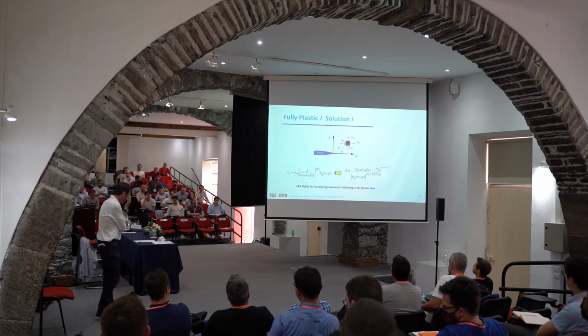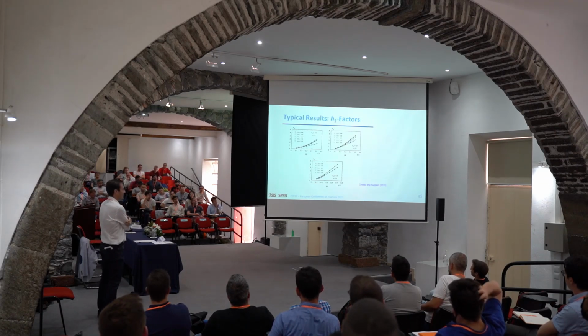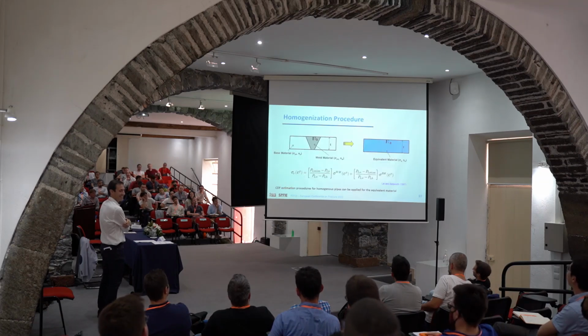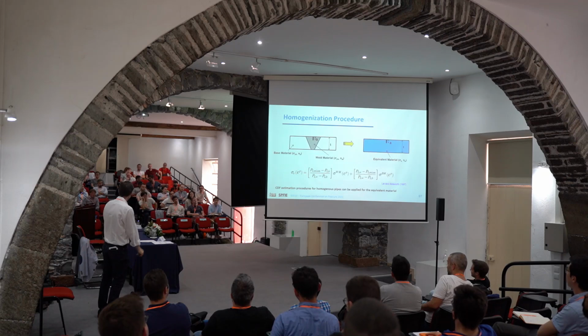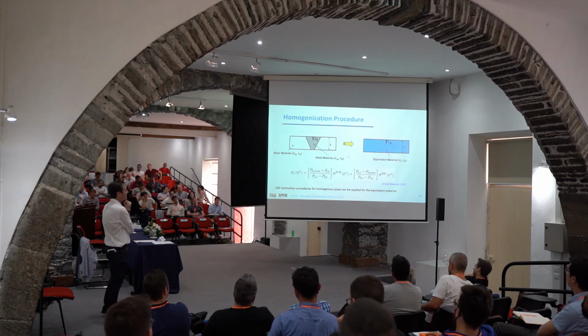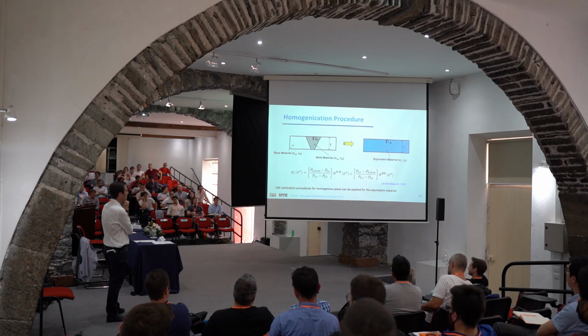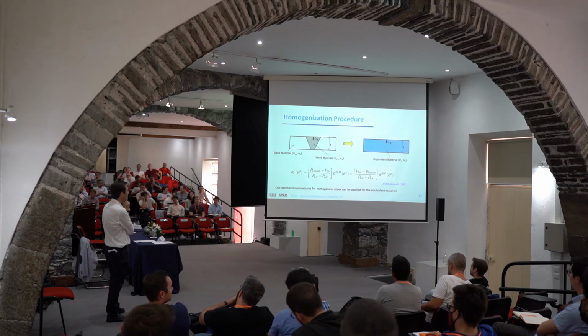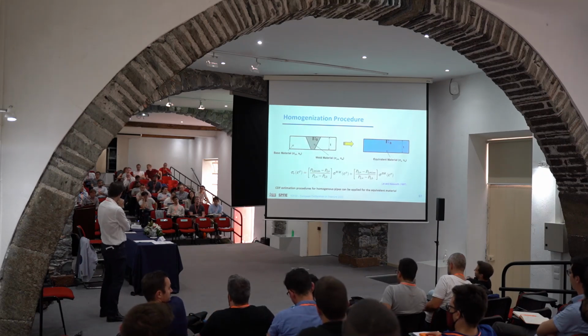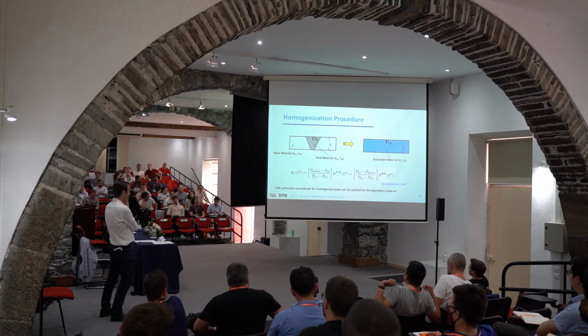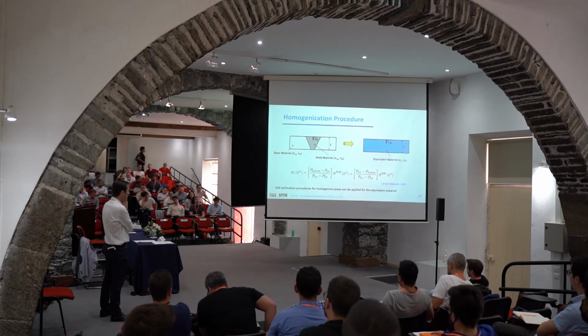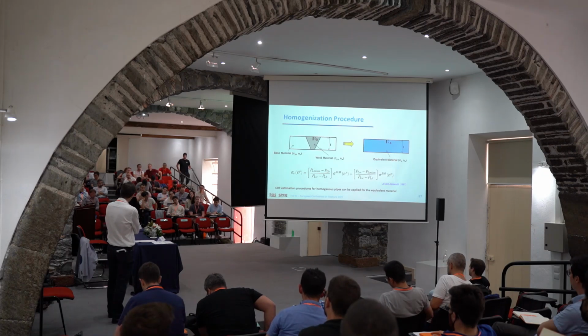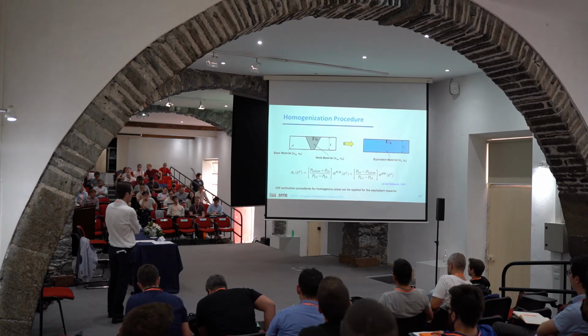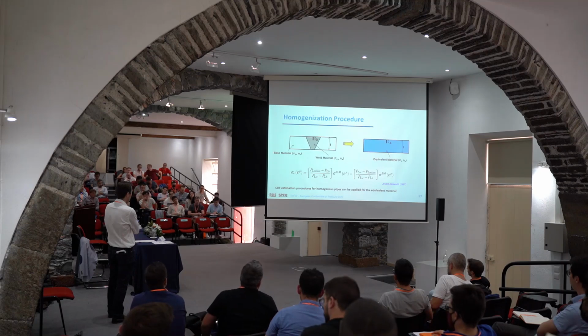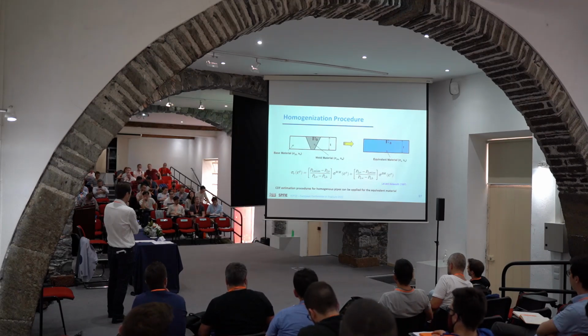Just to show you the observation here, another thing that we need to care about, again, is the mismatch, the driving force. What I showed you before is the specific details about measuring the fracture properties. On the other side is the crack driving force. It's a very important ingredient. And again, we have the similar weld material here. I'll go very quickly, just to show the final result. The procedure that we have here is kind of obtaining an equivalent material.